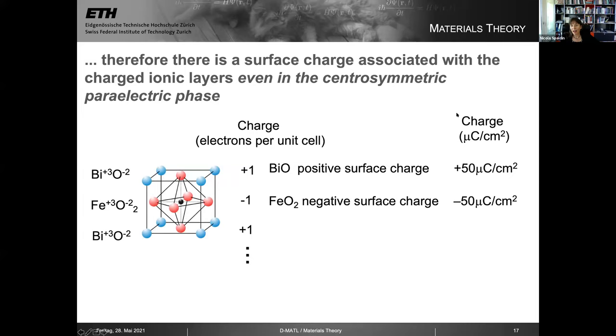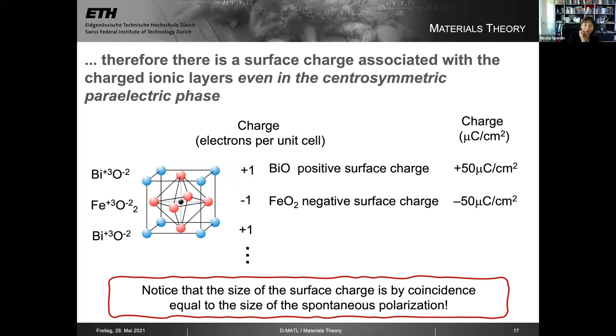And if I work out the values of these surface charges in ferroelectric units, what I find is that the surface charge associated with the bismuth oxygen surface is plus 50 microcoulombs per square centimeter. And the surface charge associated with the FeO2 surface is minus 50 microcoulombs per square centimeter. That's if I convert one electron per unit cell into ferroelectric units. And if you remember back to when we first looked at the polarization in bismuth ferrite, the spontaneous polarization in this 0-0-1 direction, the polarization that comes from the ferroelectricity when the bismuth ions displace relative to the rest of the unit cell, that also had the value of 50 microcoulombs per square centimeter, right?